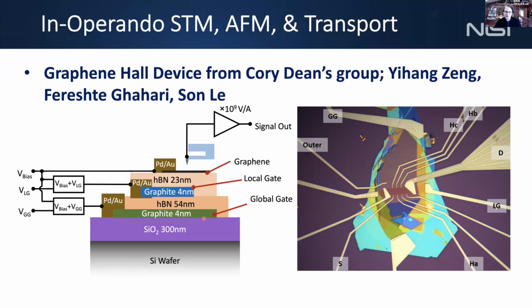So we're still using a PN junction to define the quantum Hall bar, where the outside gate can set the graphene to an electronic insulator. We know graphene is fully gapped in the magnetic field, so instead of having a physical boundary where we cut the graphene, if you try that, and we tried, the cut edge is all destroyed. It's all mangled up and has a lot of defects in it. So to have a continuous graphene sheet across the edge, we use a second graphite gate, which sets this region to an electronic insulator instead of a vacuum insulator. And it behaves the same. You see the same quantum Hall physics.